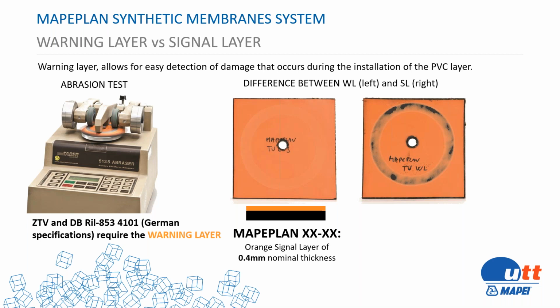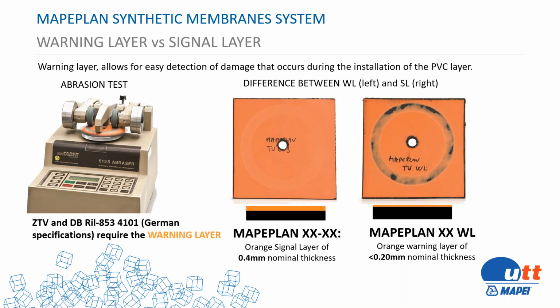And also we have a membrane that has what is called a warning layer. It is a thinner warning layer that meets the German standard. It is less than 0.2 mm nominal thickness. The advantage of this signal and warning layer is that after applying the membrane inside the tunnel, if any damage happens to the membrane, the signal layer and warning layer will be scratched and we're going to see the black color. And this is going to give us a good indication that we have an issue or need attention for repair.